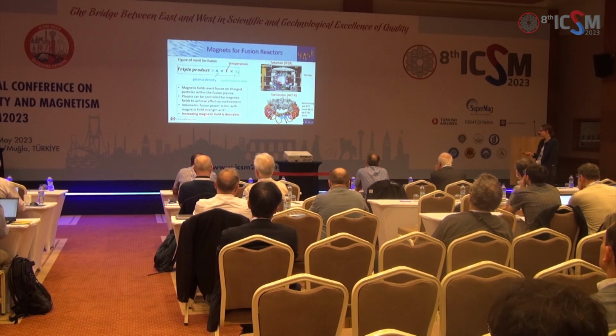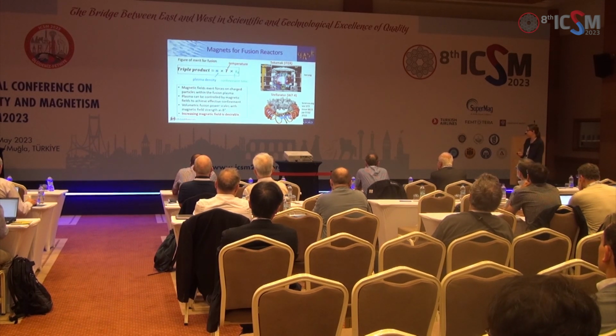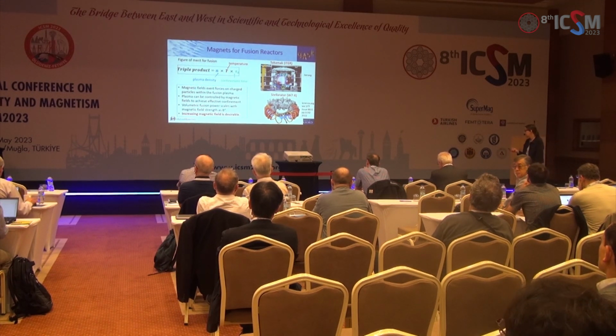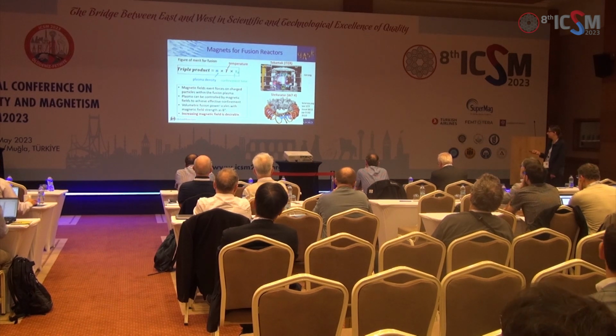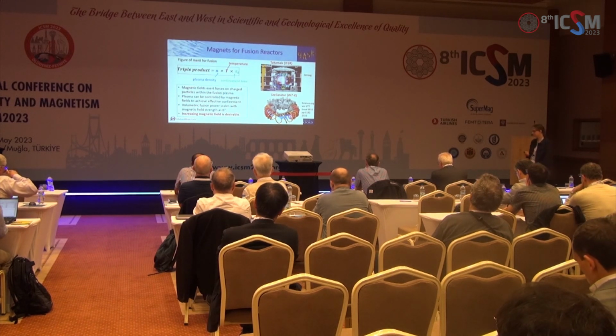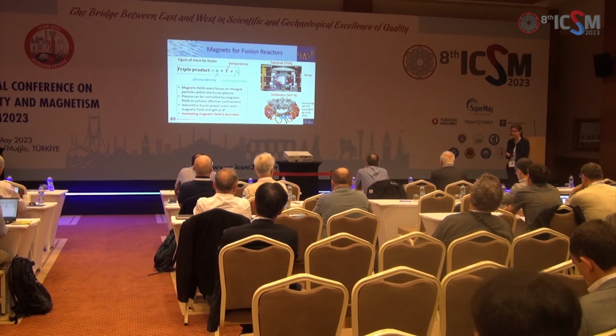Now, the other point to make is that the fusion power essentially scales as the magnetic field to the power 4, which means that the higher magnetic fields we can achieve, the more fusion power we can get. So increasing magnetic fields are desirable. And for people working in superconductors, you'll immediately realise that if we need high magnetic fields, then superconductors are a good way to do that. There's 2 kinds of device, magnetic fusion confinement devices. One's a tokamak. This is the most mature technology, I think most people will agree. And the other kind is a stellarator. And both of them are being explored. And both of them are using superconducting magnets.